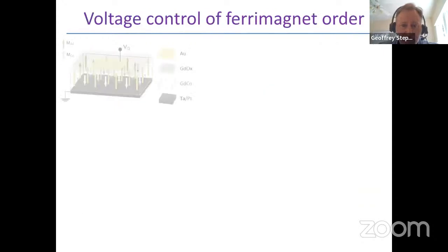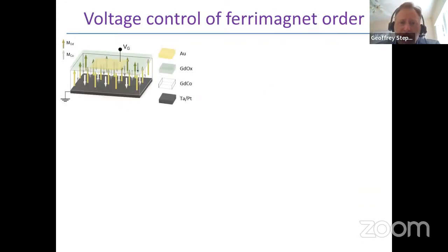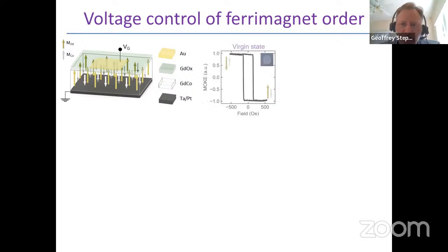And these are the typical ways in which one controls compensation in a ferrimagnet, either composition or temperature, or some combination of the two. So what we have found is that there's another way that we can do this, by gate voltage at room temperature. So using cobalt gadolinium, where we build an asymmetric structure, but on the top is an oxide that works as a good ionic conductor, we have found that in the virgin state, and I'm going to show some MOKE hysteresis loops, and the MOKE is sensitive to the transition metal sublattice. So even at compensation, if we switch the orientation of sublattices, we can see that as a change in the contrast of the hysteresis loop.